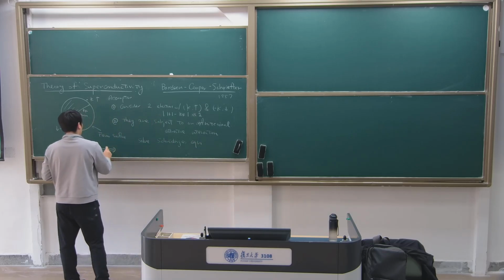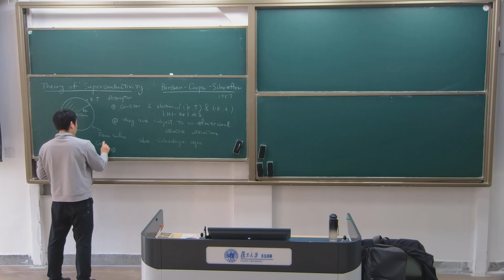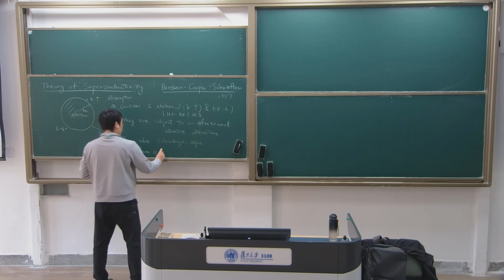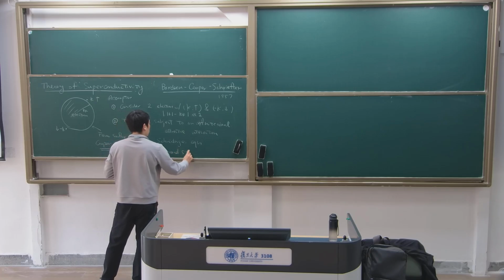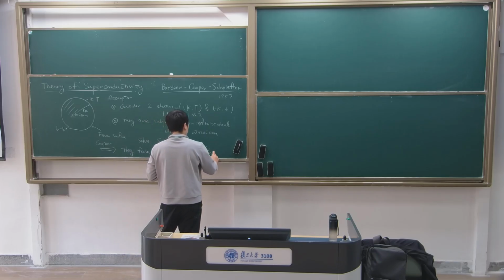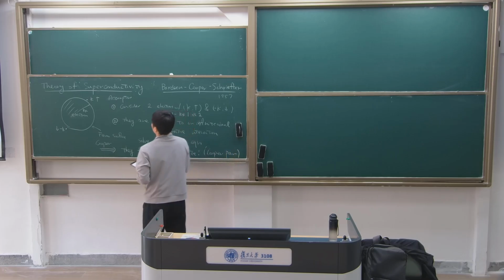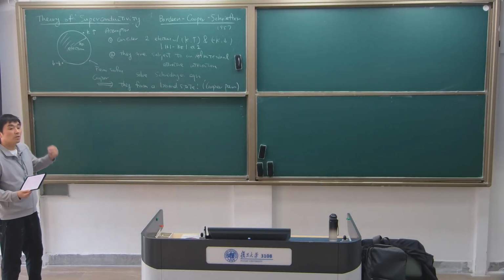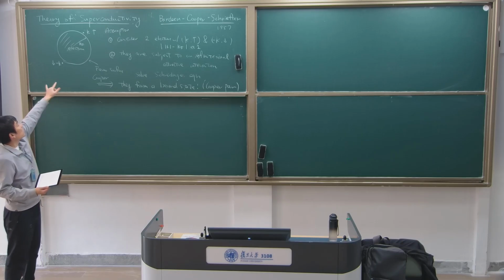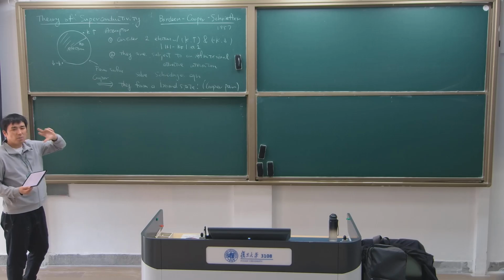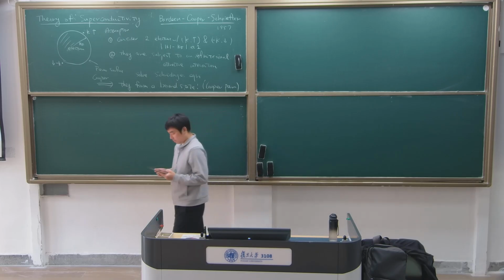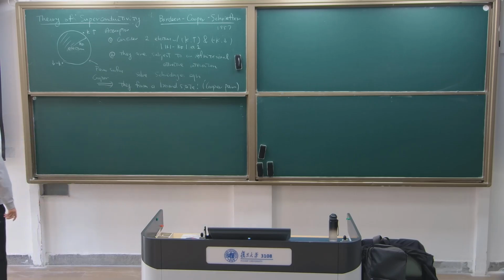And then Cooper showed there's one bound state. So before BCS, assume the two electrons near the Fermi surface with the opposite momentum and spin, and they're subject to an infinitesimal attractive interaction. And the following. That's what we are going to show first before BCS.